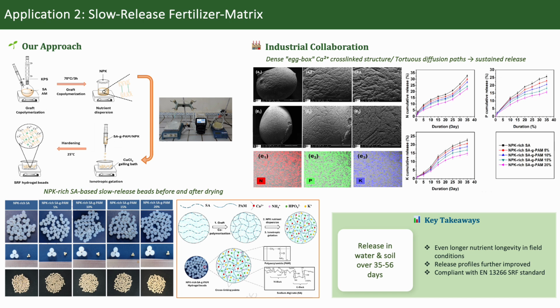In addition to coating fertilizer granules, we also developed a second strategy based on NPK-rich alginate-based slow-release beads. In this case, the nutrients are not only coated at the surface but directly incorporated inside the biopolymer matrix. The beads are formed through calcium cross-linking, leading to a dense egg box structure. These cross-linked architectures create tortuous diffusion pathways which slow down nutrient migration from the bead to the surrounding medium.